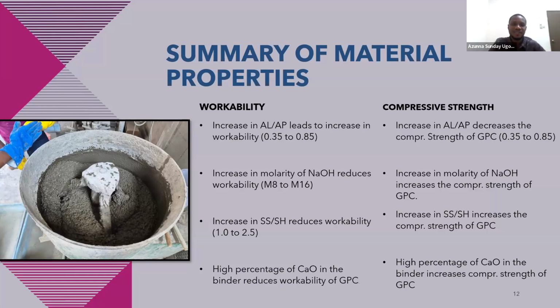So if you look at this, you begin to wonder, how can I now design my geopolymer concrete to give me my desired strength properties? Because for, let's say, mass concrete, you can decide to use a low molarity, a low ratio of alkaline liquids to binder ratio, where the strength is not an emphasis. Maybe you need 20 MPa. So you can reduce this and you have a high workability and a strength that is not too high, and you'll be able to do your casting.